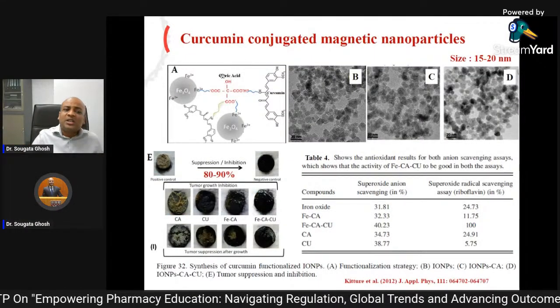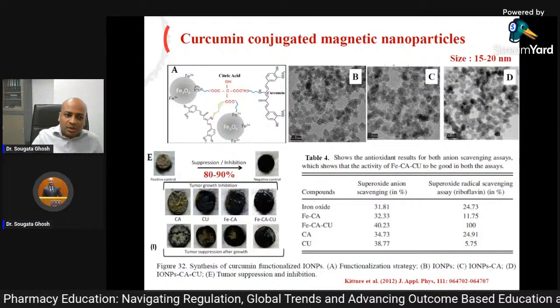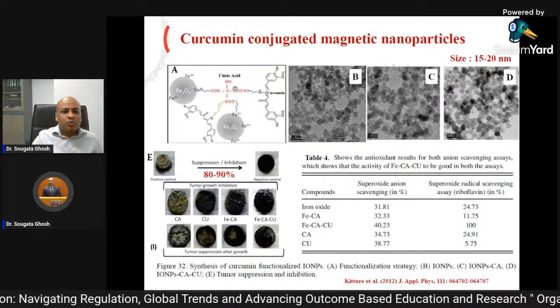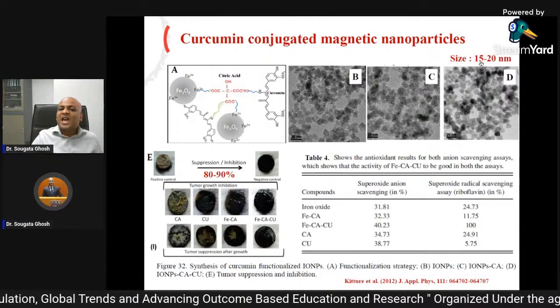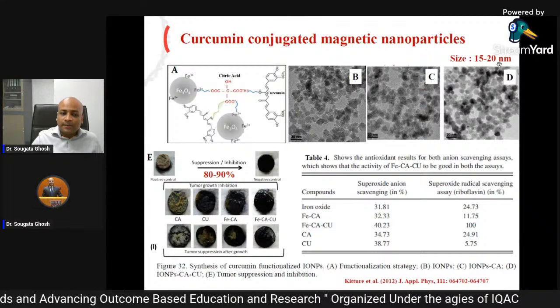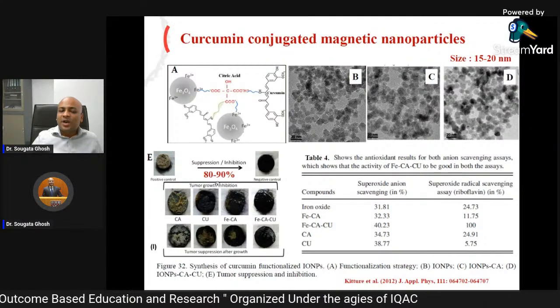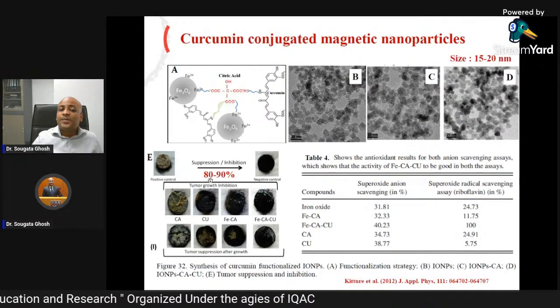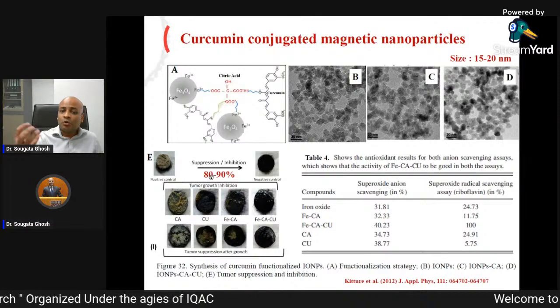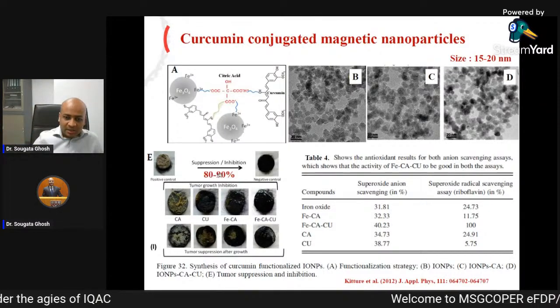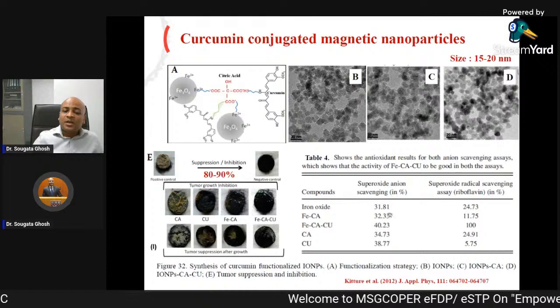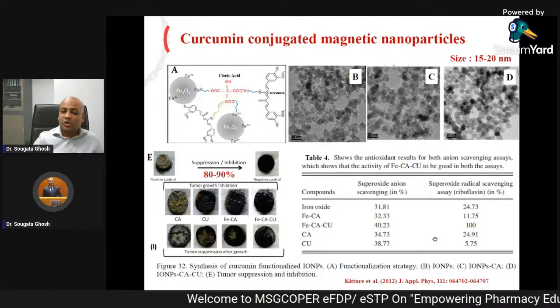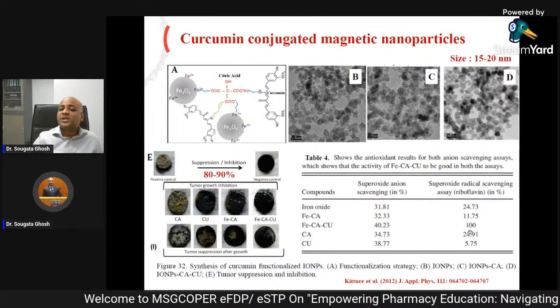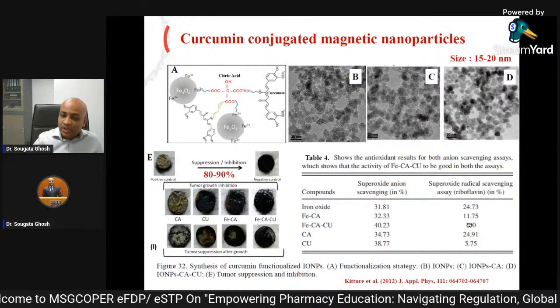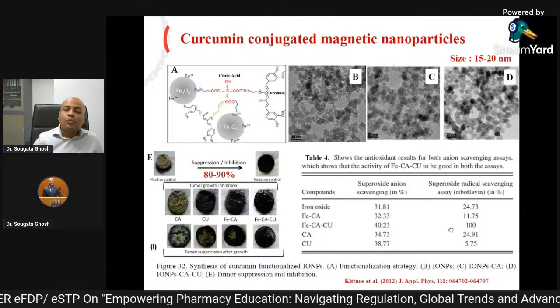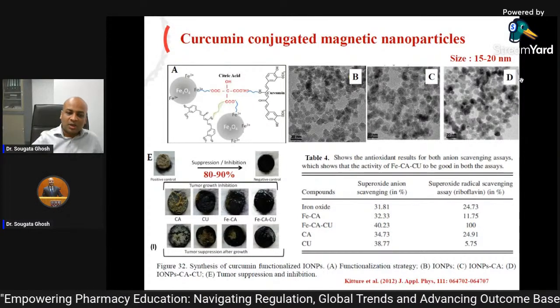So we conjugated this curcumin onto iron oxide nanoparticles with a citric acid bridge, and the size was 15 to 20 nanometer. It could inhibit the tumor up to 90%. 90% tumor inhibition, when curcumin was conjugated to iron oxide. And it could also scavenge the free radicals. You can see superoxide, 100% free radical scavenging over here. 100%. So potent this compound was.